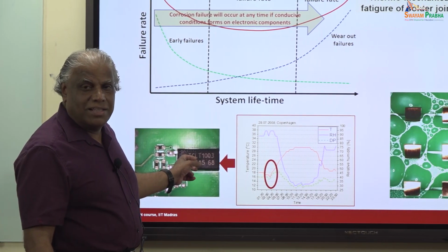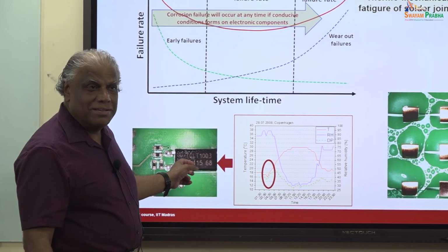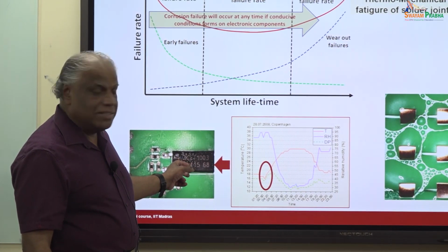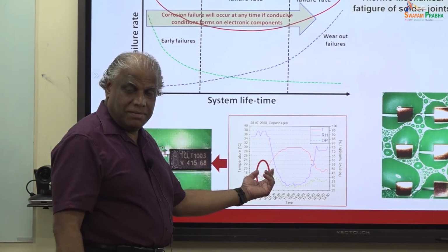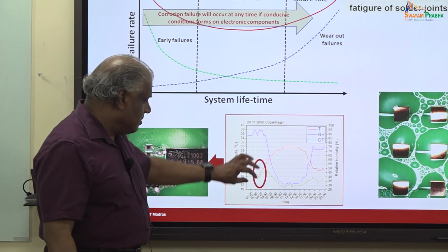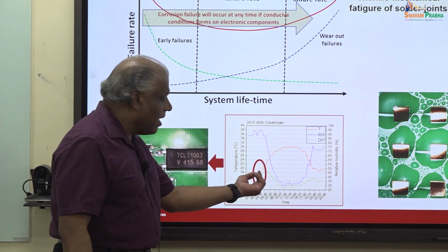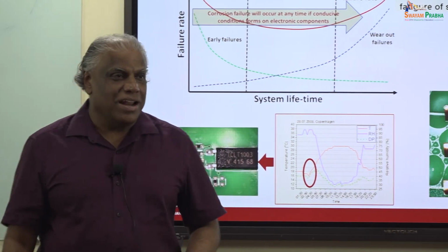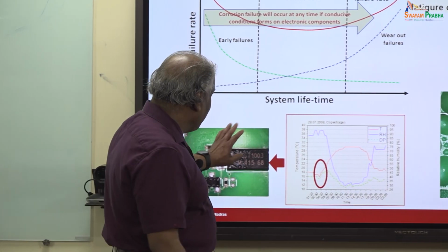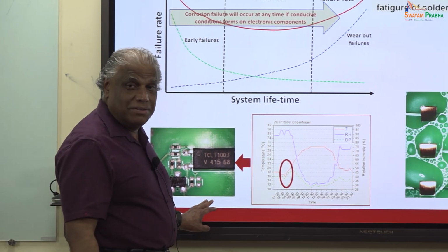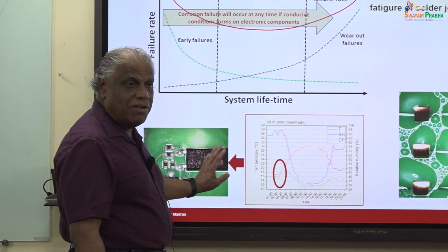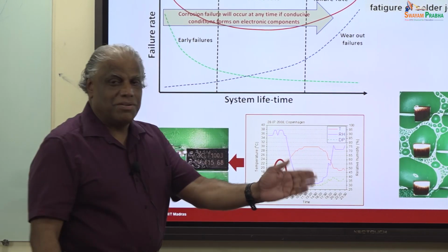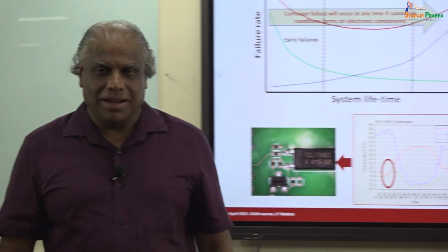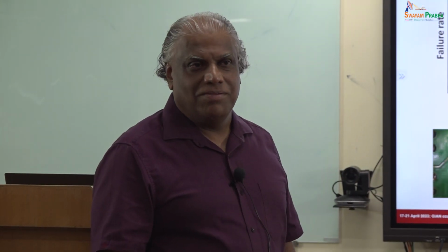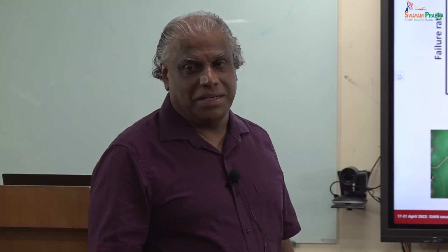Like I was saying yesterday, the solar energy is not producing in the evening and the night, so they will shut off. And that's a period where they can get this 2 hour period. Within that 2 hours, maybe only half an hour is critical. If in that half an hour you can avoid forming condensation, or even if condensation is forming, you can avoid the failure, then you get robustness, right? Then it adds up, and the system will work like that. Every day you may get condensation, but it does not fail. The system will work like that for a 10 or 20 year period.